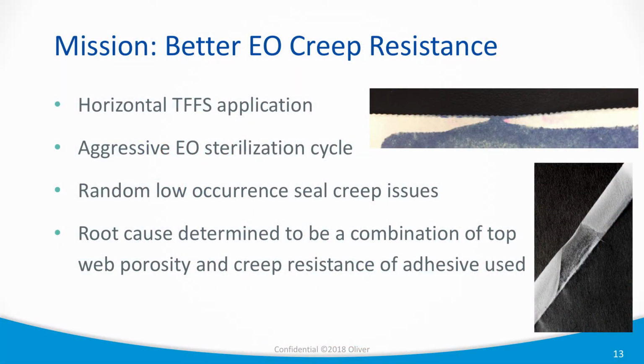Okay, pass it back. So one last case study. This one was related to ethylene oxide, EtO gas creep, so seal creep during EO sterilization. And it was a reinforced coated paper, and it was a horizontal form fill seal application. In this particular situation, the manufacturer of the device had shifted EO cycles to a much more aggressive cycle, and they got through validation okay, but over time they started seeing very low occurrence rates of open packages. And that picture on the right side, you can see that's a dye penetrant test failure.